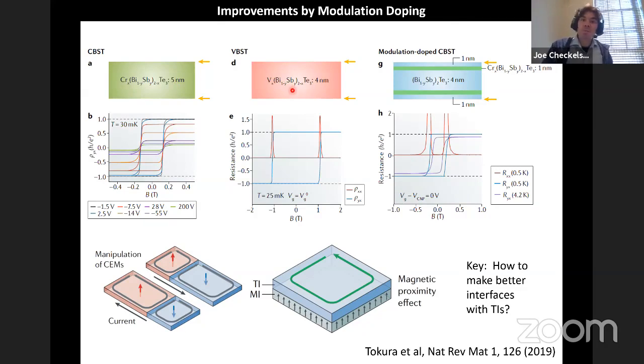But some of the most beautiful work came from leveraging some of the degrees of freedom that you get in thin films, which is basically being able to modulation dope these systems. Although some people might argue about what's being done here, you're selectively putting chromium into one part of the film. What they showed by doing that was, at least in a very rough picture, you can imagine they're keeping the film pristine in some areas and confining the magnetism to other areas.